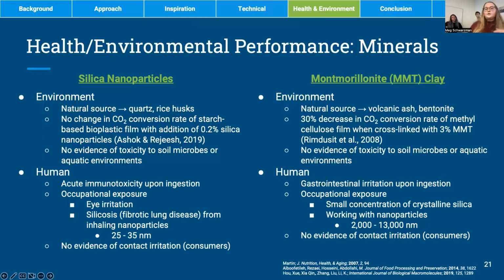So a little bit of a red flag there that it would slow down that process. And then on the human side, we share that same occupational exposure concern because MMT does contain a small concentration of crystalline silica, and it would be in nanoparticle form. The nanoparticles are much larger than those silica nanoparticles, and there is just a small concentration of that crystalline silica, but nevertheless, we're still concerned about the possibility of working with those materials, introducing the risk of silicosis to workers.